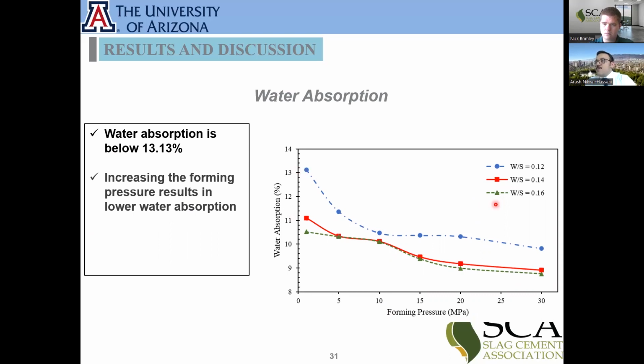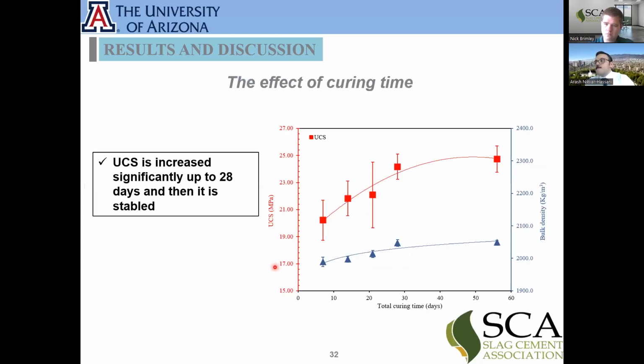The sample with 20 megapascal forming pressure and 14% water content has only 9.2% water absorption. So we are meeting the compressive strength criteria and also the water absorption. Now let's do some durability tests on the samples and see how the material acts. The first thing we did is the freeze and thaw cycle.